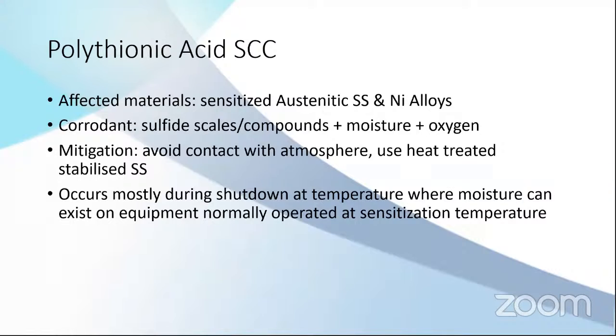When it's in operation, its temperature is very high. So the equipment is operated at the sensitization temperature, 500 to 800-something Celsius. So they get sensitized. They get chromium carbides. But because the operation is at high temperature, there is no wet corrosion. So it's no problem actually for the equipment to operate. You won't have corrosion because it's dry.